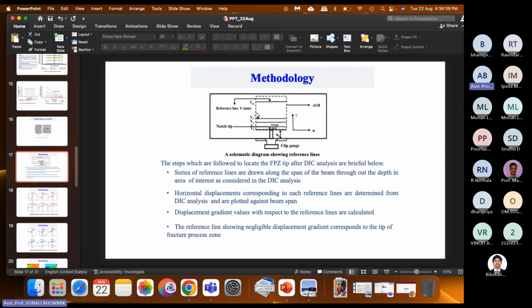So what was the study within this straight line of Y3, Y2, and Yn? What is the displacement? That means the horizontal displacement of each particle has been analyzed. So from this data, as I mentioned, in deformed data, this displacement point can be located. So using those data, how much displacement occurred has been computed within this methodology.